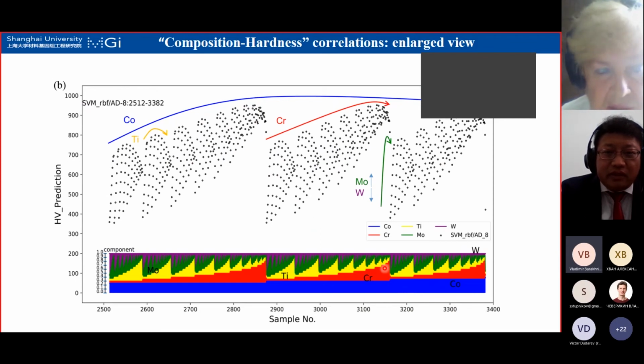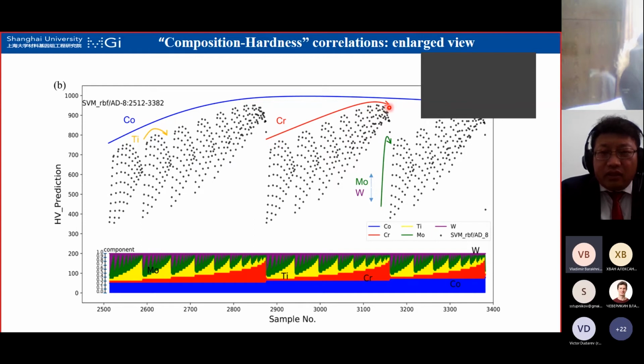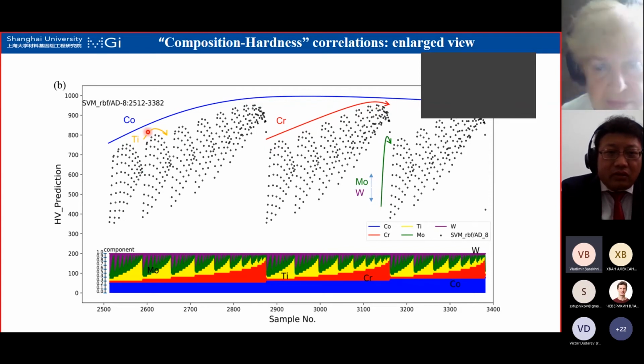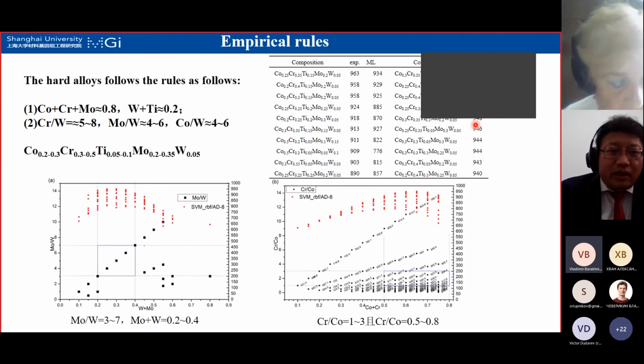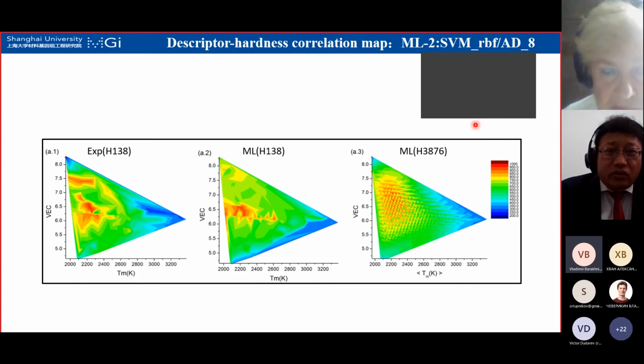For example, I enlarge part of this so we can find the trend. This curve reflects the molybdenum and tungsten effect, and we can see there's a peak. This is a curve of curves, an envelope of curves. The maximum of this curve envelope corresponds to chromium, this one corresponds to titanium, and this one corresponds to cobalt. So basically, we can optimize the composition for the best target. Also, we can summarize this result and get empirical rules. We can also build a descriptor-hardness correlation map. For example, in this case, the valence electron concentration and the melting point can give us a prediction of the hardness.